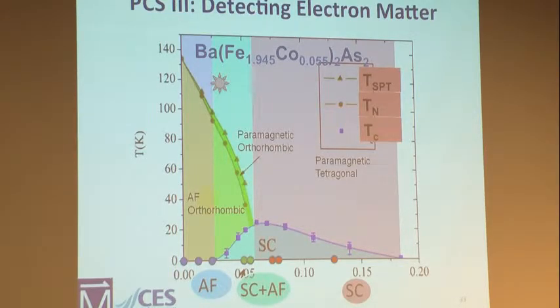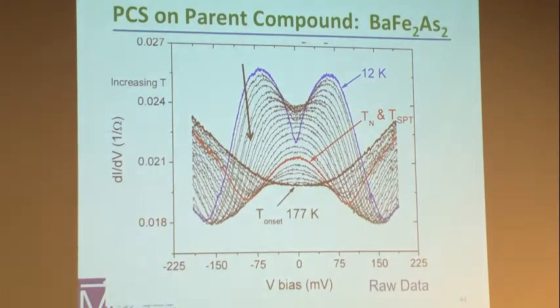Because we didn't know from nothing, okay? We didn't know what to expect. So he goes and measures this stuff. Let me just show you. He's looking at the parent compound. This is 135 degrees and no superconductivity. And these are some data where it shows at 175 degrees, we see a funny shaped background conductance. And as we lower the temperature, we start getting enhanced conductance around zero bias. Just to be perfectly honest, we don't understand the upturn in the background conductance nor that dip in the center. We have an idea what it is, but don't look at that. Now that I've told you that, that's all you're going to look at. Anyhow, concentrate on the enhanced conductance here.